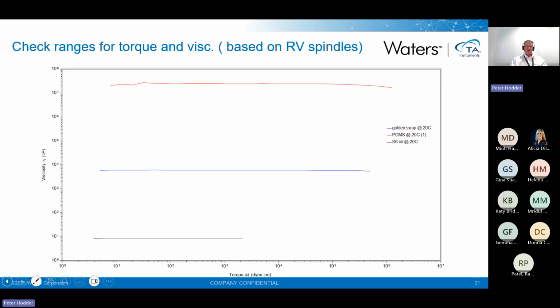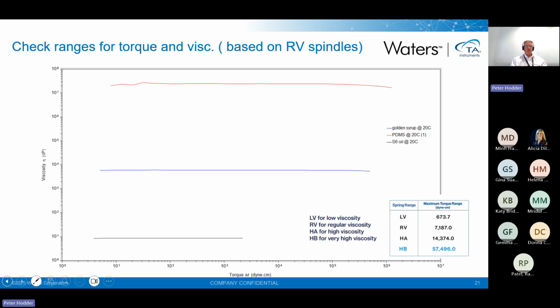But what's interesting is if I consider the actual physical torque ranges of the instruments, which are put in the bottom right-hand corner, and put those on the graph, what I see clearly is that the LV can't actually measure the low viscosity materials. It doesn't matter what spindle. Remember, the top and the bottom ranges are based on the spindles used. So it doesn't matter what I do, I can't measure a low viscosity fluid. If I take the RV system, then I've got even less chance. But what I can see is that I'm in close to the middle or to the low end of the range for measuring golden syrup.